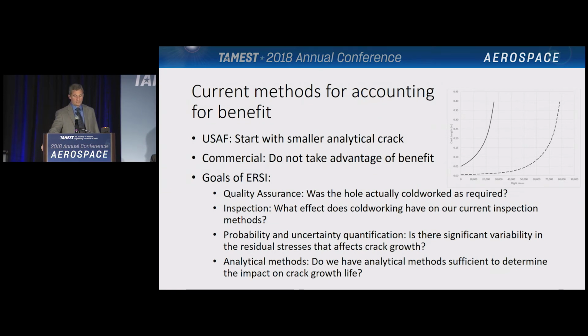Next, is there significant variability in the residual stresses that can affect crack growth? Or to put it another way, will a small change in any of our inputs cause a large difference in crack growth lives? If so, we need to understand that so we can be conservative in any of those areas and not overestimate the time it takes for cracks to grow. And then finally, do we have analytical methods sufficient to determine the impact on crack growth life? We need to be able to model the process and understand the stresses in the material and how those stresses affect growth.